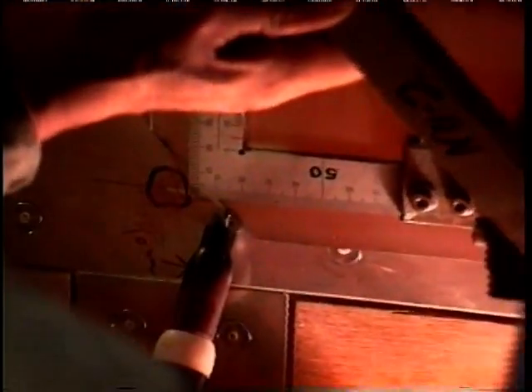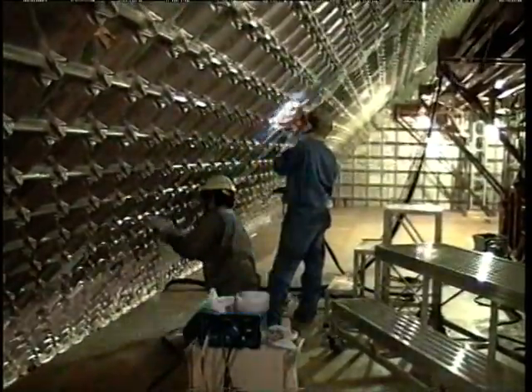The sheets are then welded onto the insulating block by discontinuous welding on the anchor strips, which have been inserted into the upper plywood. The sheets are welded by continuous welding onto the adjacent sheets by an automatic welding robot. The welding uses a high-reliability TIG process without filler metal.